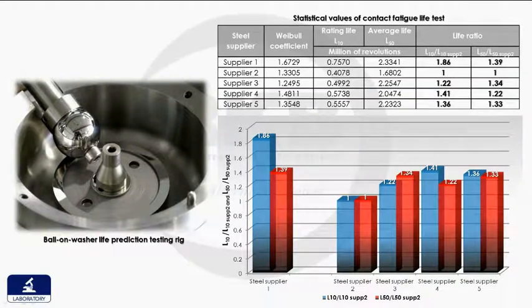Life prediction test is another important task habitually accomplished by our mechanical testing laboratory to approve any new supplier of raw materials. By way of example, a contact fatigue life test was carried out to check the quality of the steels proposed by 5 potential raw material suppliers. The material test specimens were annealed and manufactured as washers, hardened in a gas-protected electro furnace between 835 and 845 Celsius degrees, and finally tempered between 150 and 160 Celsius degrees for 3 hours.